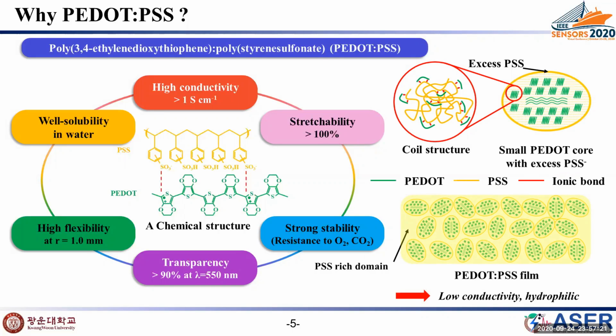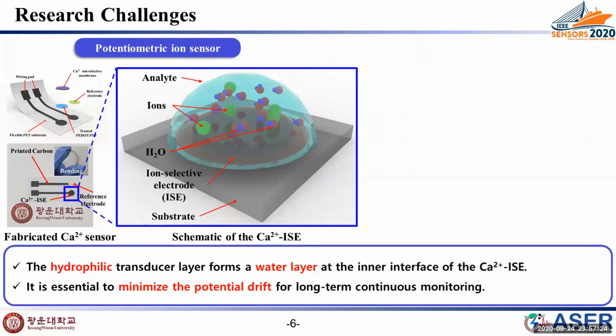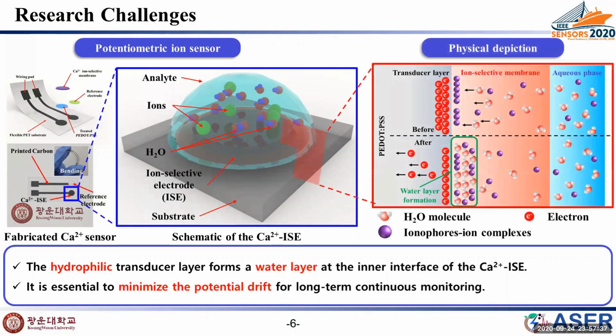and randomly oriented grains. As you can see, the potentiometric ion sensor consists of a reference electrode and an ISE, including a transducer layer and an ion selective membrane. When the sensor's ISE contacts the analyte, water molecules and target ions can pass through the ion selective membrane. At this time, the higher the hydrophilic properties of the transducer layer, the more easily water molecules are pushed to form a large water layer. And this aqueous layer causes a potential drift over time. Therefore, reducing the hydrophilic properties of the solid contact material is a way to be stable.